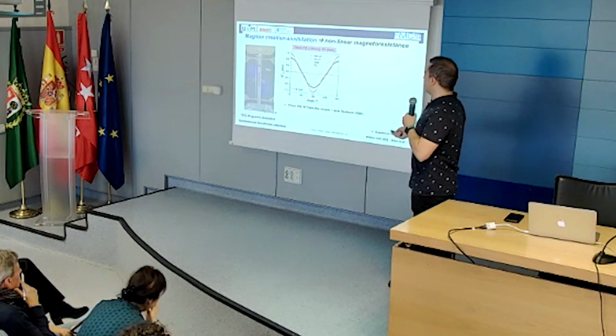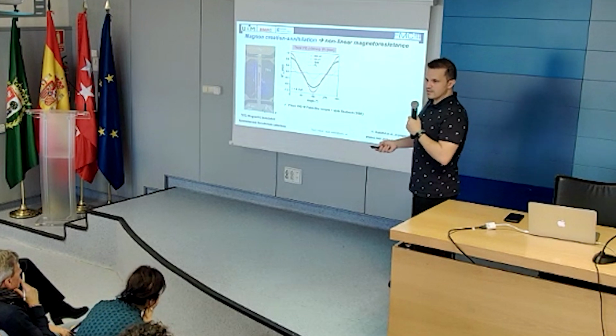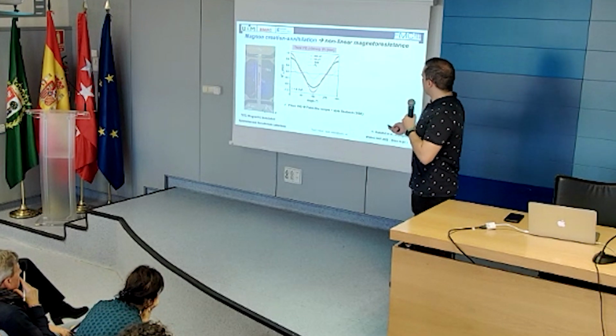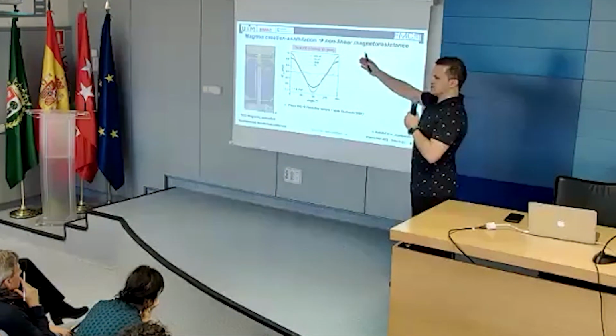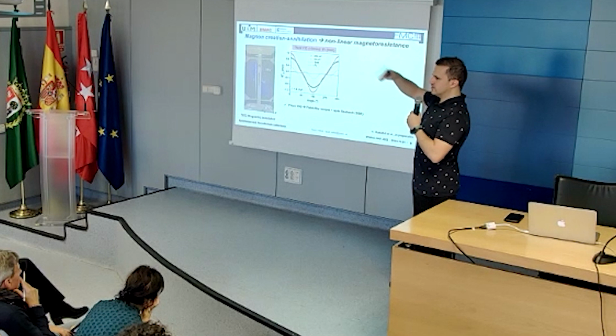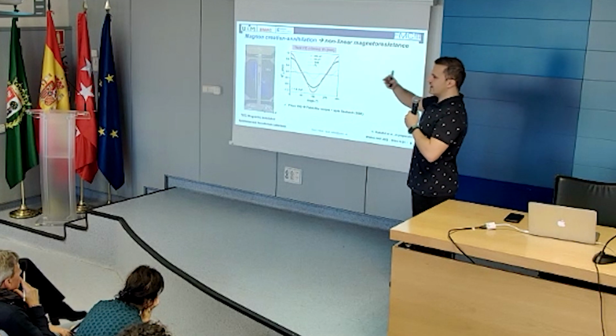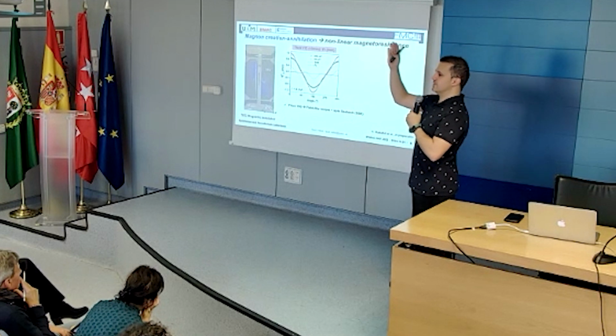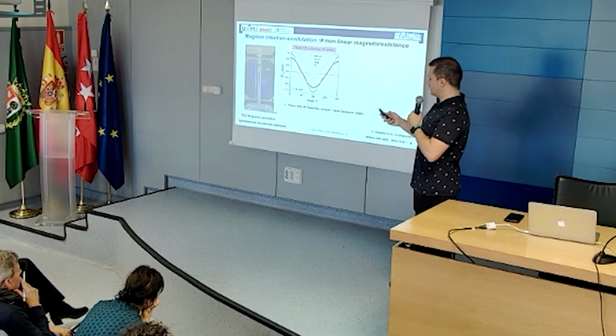We are working with platinum on top of yttrium iron garnet. When you apply a very large magnetic field to control where the magnetization is going, you see that you have applied an AC current, and these oscillations you are damping, right? So you are getting small damping.